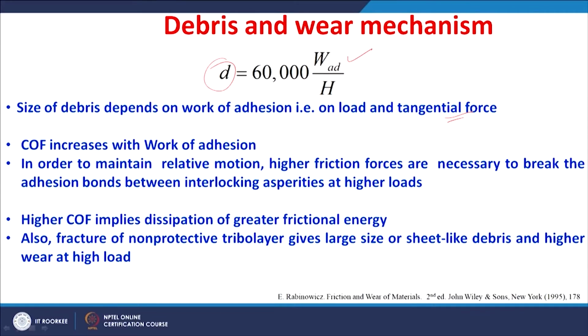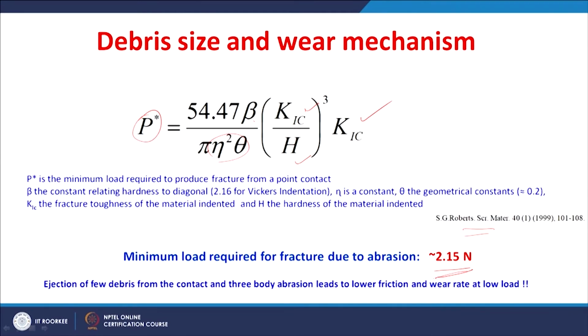In order to maintain the relative movement, higher frictional forces are necessary to break the adhesion bonds between the interlocking asperities at higher loads. So, a higher coefficient of friction implies dissipation of a larger frictional energy. The higher coefficient of friction and wear can also be understood by the non-protective tribolayer nature. We have seen the tribochemical layer formation and then its cracking, which indicates the non-protective nature. The non-protective tribolayer is fractured and gives the larger, sheet-like debris and correspondingly higher wear at a higher load. So, these two mechanisms, abrasion at a lower load and adhesion with the corresponding tribochemical wear at the higher load, can be understood right from the debris size.